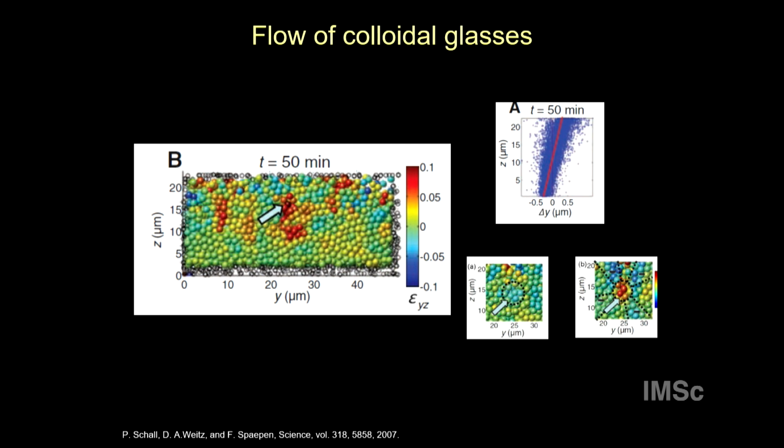This is just the displacement of all the particles in the direction of the shear as a function of the distance between the boundaries. So you have a more or less linear profile, and they were able to see these kind of rearrangements. This is at time t equal to 0, and when you apply stress on the system, you see that a quadrupolar region develops here. And they showed that it is long ranged. Everything was done using these kind of pictures. So this was the first step that they took to understand how these systems fail.